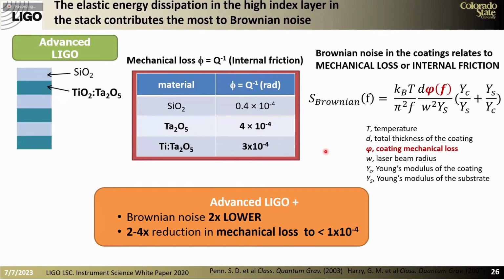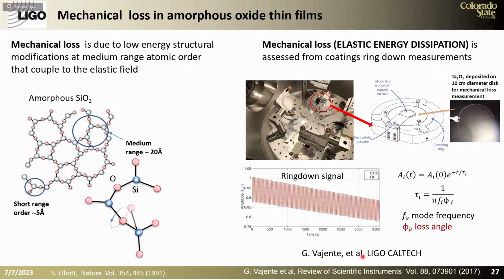a mirror is in the cavity, in the interferometer. So the coatings that LIGO presently uses are a combination of silica as a low index layer and titania doped tantala for the high index layer. And the studies have shown that it is the high index material that contributes the most to the mechanical loss. And mechanical loss is related to Brownian noise through this expression. So by lowering the mechanical loss, we can actually reduce the